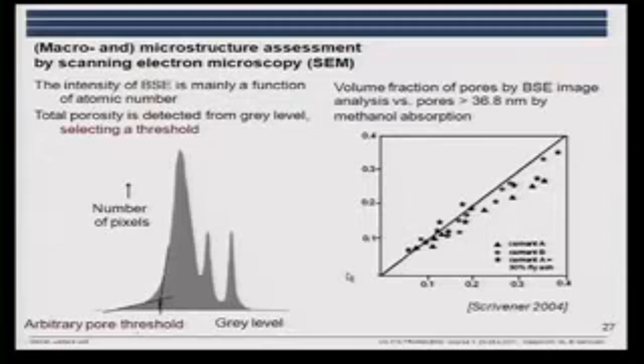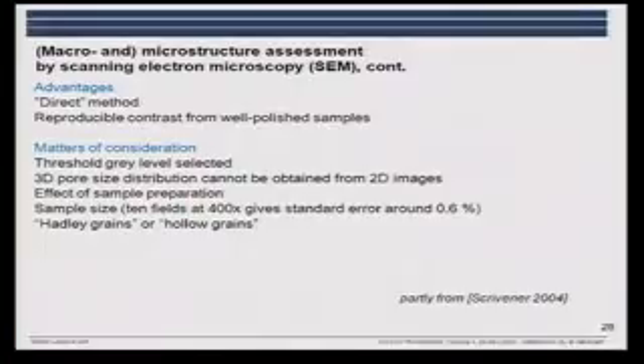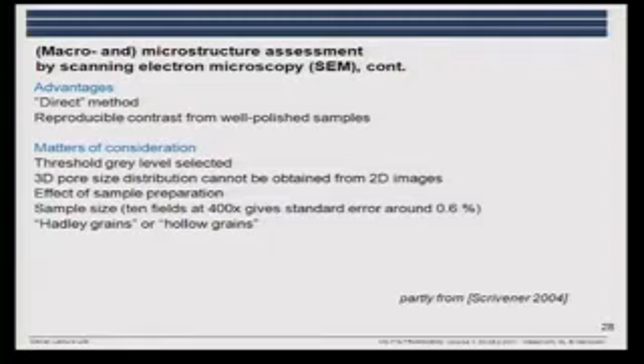Here you have a graph showing the comparison of volume fractions determined by backscattered electron or scanning electron microscopy and image analysis, and then methanol absorption. And that compares quite well. So the advantages of this method: it's direct and reproducible, with contrast from well-polished samples. Of course, you need to be sure that you're actually impregnating the porosity, and the samples need to be well-polished. Matters of consideration: how do you actually determine the threshold, the gray level? And coming to pore size distribution, you cannot determine it from 2D images. You have the impact of the sample preparation, and then you need a lot of samples or images to have a reasonable accuracy of your data.